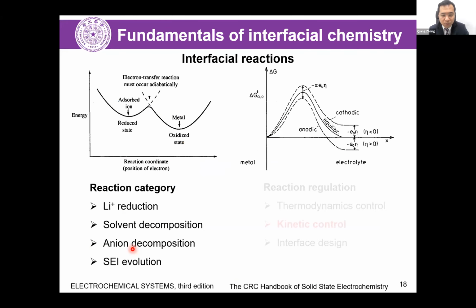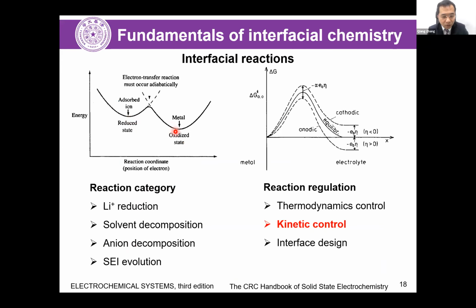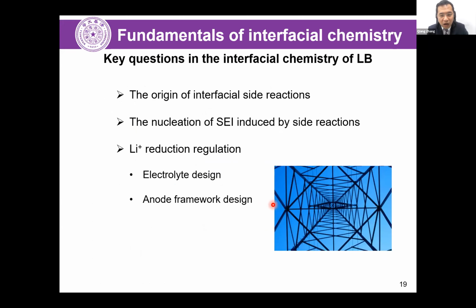So in this case, it is possible to carefully describe what happened between the electrolytes and the metal anodes. And in this case, we try to probe not only from the viewpoint of the thermodynamic control, we also can probe what happened from the viewpoint of kinetic control and try to control the interface structure. So in this case, we try to answer what's the origin of interfacial side reaction? What side reaction happens there? And also, there are a lot of solid products deposited on the surface. So what are the solid products, and can we regulate the composition and its distribution?